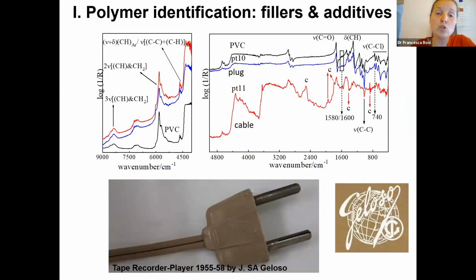Furthermore, through FTIR, we are also able to identify the possible presence of other inorganic or organic fillers or additives, as in this case, the cable and the plug of the tape recorder I showed you before. In the case of the cable, we detected, along with PVC, present also in the plug, the presence of calcium carbonate as a filler. And you see here from this comparison that both in the plug and in the cable, we still see polyvinyl chloride as the main polymer constituting the plastic, although you see that the spectra are very different.